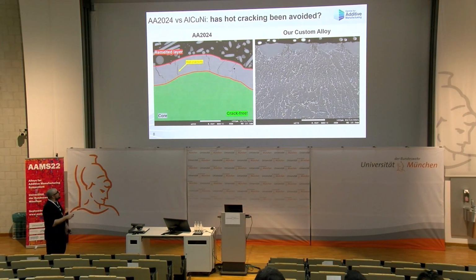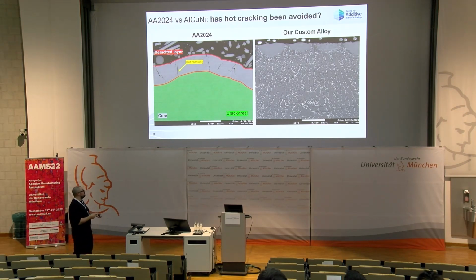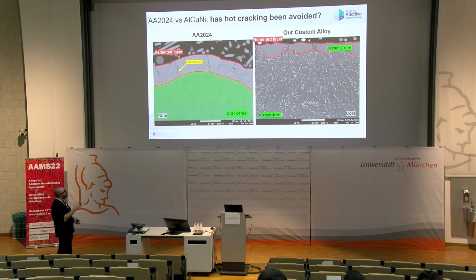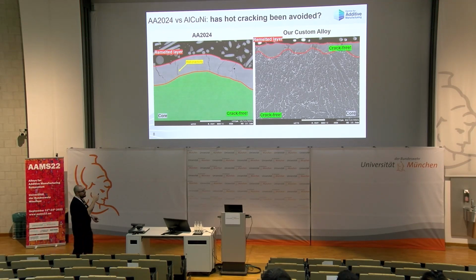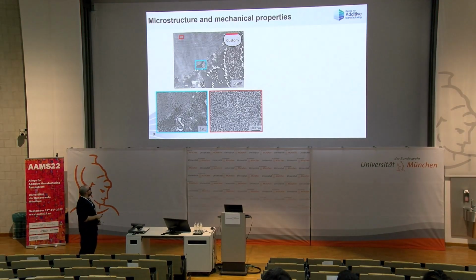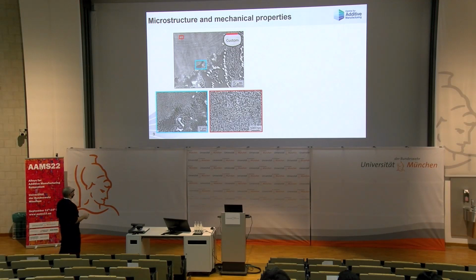But the remelted layer has a very similar microstructure in terms of cell size and, of course, also molecular arrangement. What we can see here is a crack-free microstructure in both the remelted layer and the core. If we look at the interface between the remelted layer and the core, we can see a progressive change towards a very refined microstructure in the remelted layer. Here, cells are around 300 nanometers in size, so they're very small.